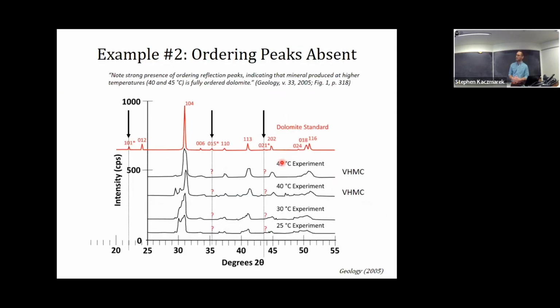Here's a study from Geology 2005. The claim here: note the strong presence of ordering reflection peaks indicating the mineral produced at higher temperatures, 40-45 degrees, is fully ordered dolomite. What I've got here is the data presented in this paper, and the red curve here is the dolomite standard. What I want you to see is that this 104 peak matches up pretty well with a peak that they have in their experimental results.